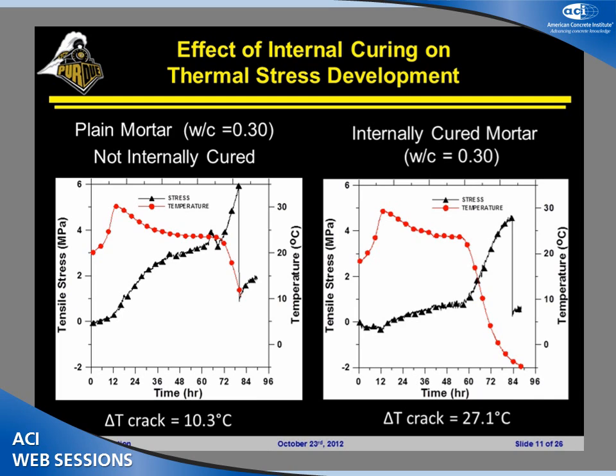The basic idea is the plain system, we can see we cast it, the stresses build up slowly over time. At 3 days, we can see they rise quickly, and the reason they're rising quickly is because we're dropping the temperature right around the 3 days. What's interesting about this plot over here is we drop the temperature 10 degrees Celsius, roughly 20 degrees Fahrenheit, and the system cracked.